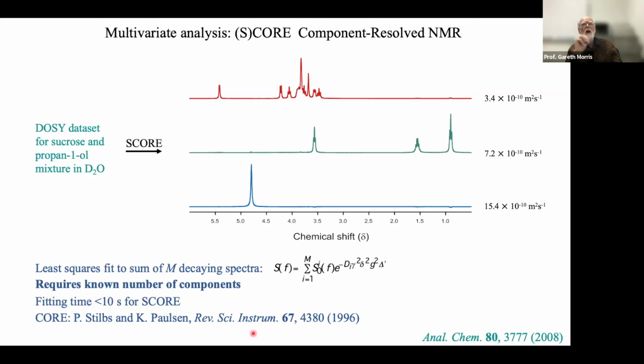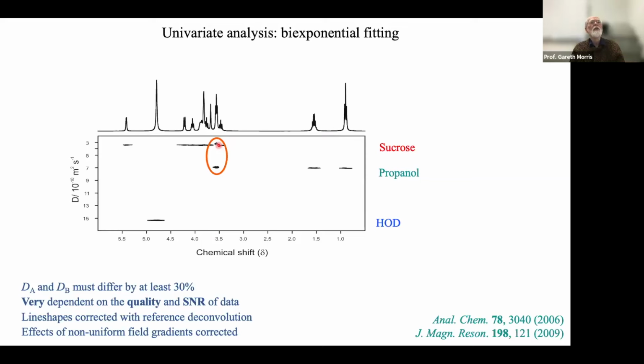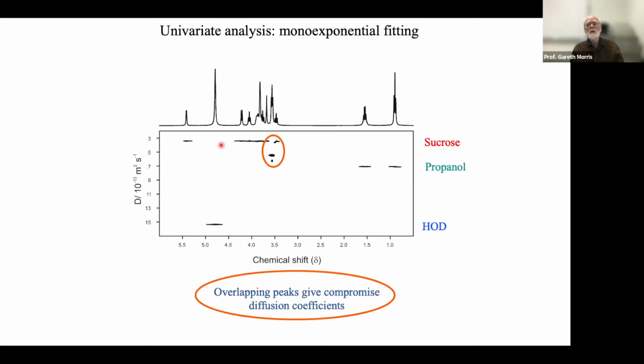And there's a nice algorithm for this, which was developed by Peter Stilbs. We found a way to make it go quite a lot quicker. So it went from CORE, component resolved NMR, to SCORE, speedy component resolved NMR, but it's basically the same idea. And if you have good data and you have a good difference in diffusion coefficient, then you can, as here, get really very nice results. And so where our signals overlapped and gave us an okay result of bi-exponential fitting and a very not okay result of mono-exponential fitting, SCORE analysis, multivariate analysis can really do very well. The snag is that real mixtures very rarely contain only a small number of components, and I've never got it to work for more than four.